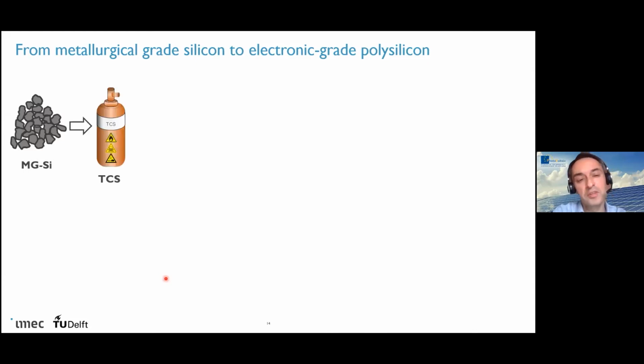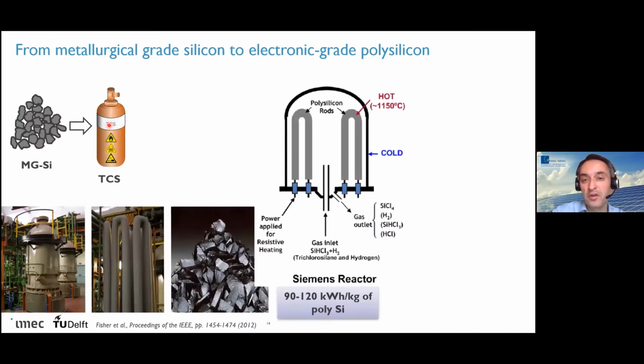Typically, this metallurgical grade silicon is further purified to make it electronic grade silicon, and it is typically done in the gas phase. So we actually make a very pure gas, like trichlorosilane in this case. Once we have this very pure gas, we can make so-called polysilicon rods. Traditionally, this is done in the so-called Siemens process.